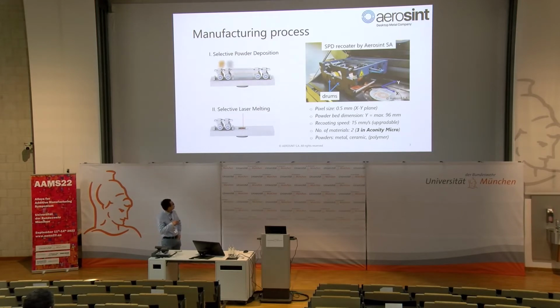And since the Y direction is limited by the length of our roller, at the moment we can only do 96 millimeter in the Y direction. The X direction is not affected. The recoating speed is lower than single-material LPBF, but we will also be able to upgrade that. We already have run internal tests which can run up to 300 millimeter per second.